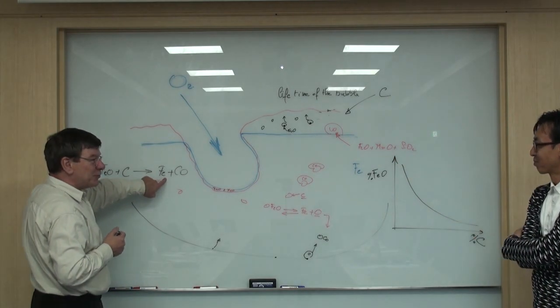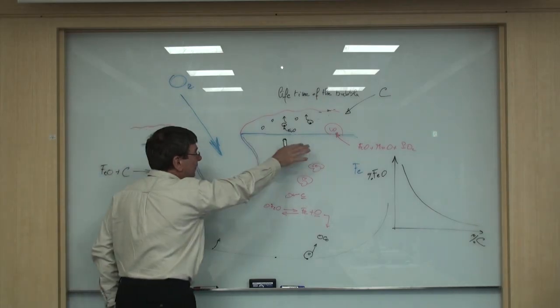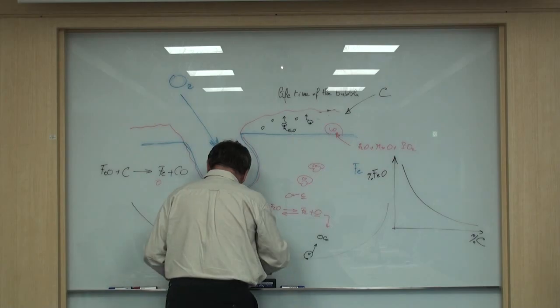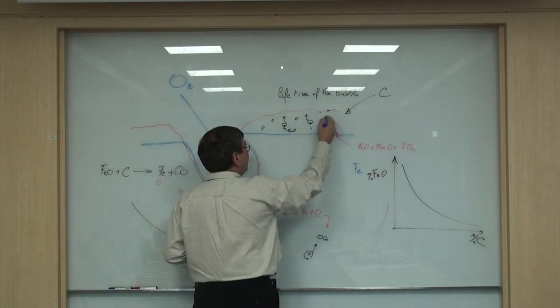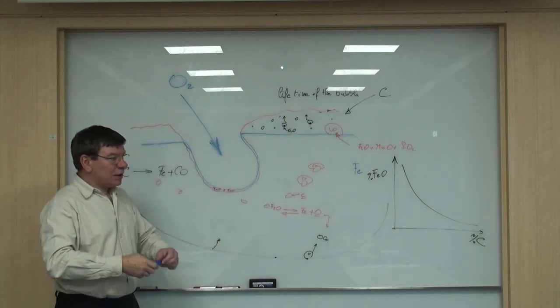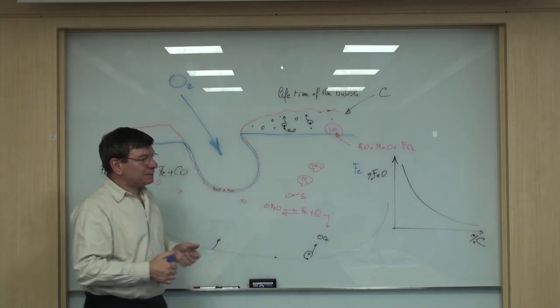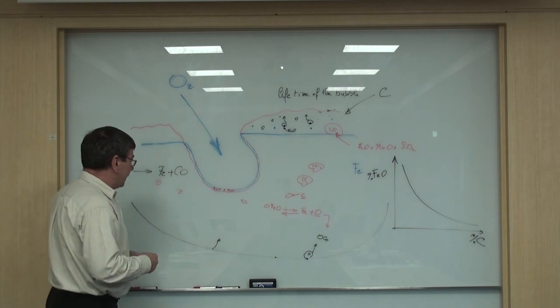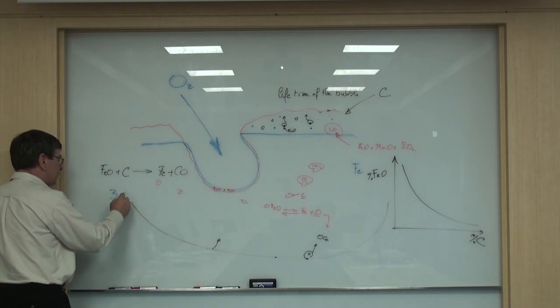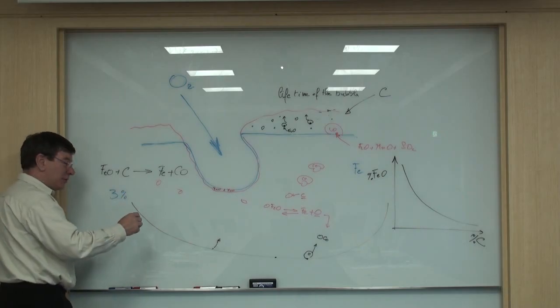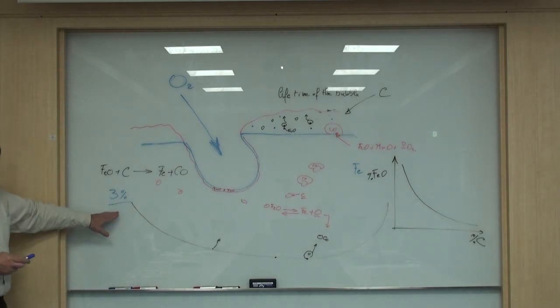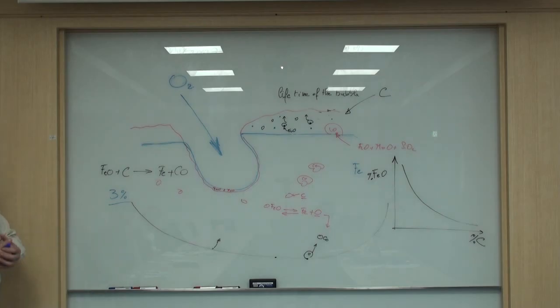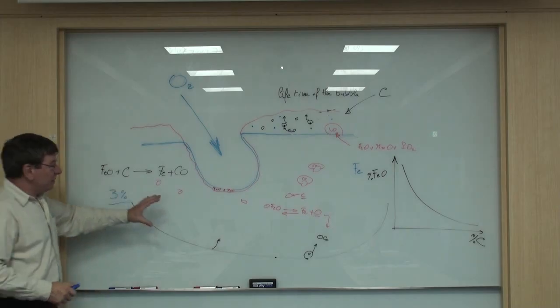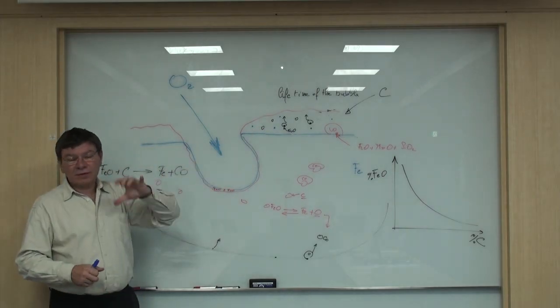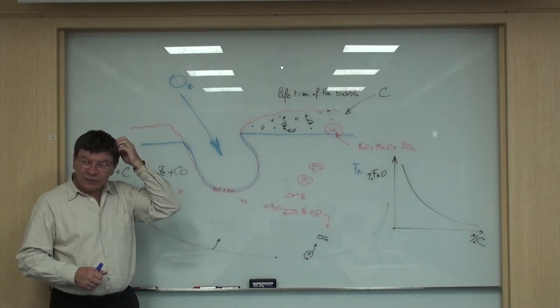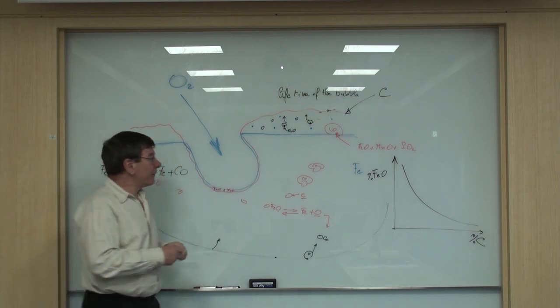You create Fe, you reduce the FeO content of the slag, and you have a lot of Fe in the slag. If you take a sample with a spoon of the foaming slag, first you find bubbles, and you can have down to only 3% of material in the volume. That means you have 97% of gas and only 3% of condensed phase, for a good foam. But this is not the point. In this sample you take, you still have 15 to 20% metallic iron.